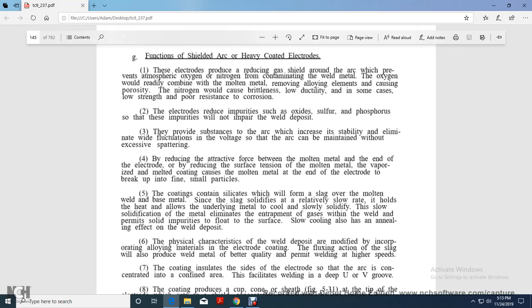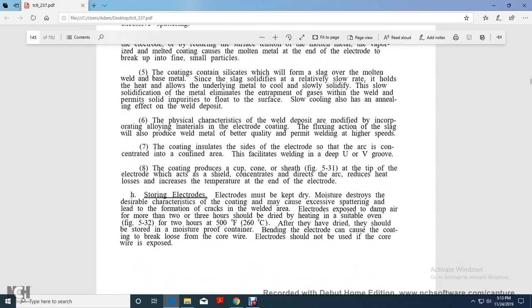2. The electrodes reduce impurities such as oxide, sulfur, and phosphorus, so the impurities will not impair the welded deposit. 3. They provide substance to the arc, increase the stability, and eliminate wide fluctuations in voltage so that the arc can be maintained without excessive spattering. 4. They reduce the attractive force between the molten metal and the end of the electrode, reducing the surface tension of the molten metal. Vaporizing metal coating causes the molten metal at the end of the electrode to break up into fine small particles. 5. The coatings contain silicates, which will form a slag over the molten weld and base metal.